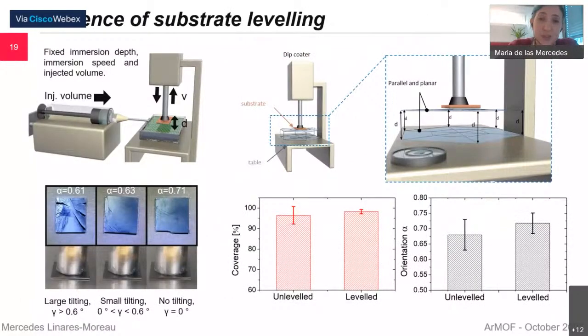The first parameter that we identified as very relevant was the leveling of the substrate. It's not that we tilted the substrate on purpose, but we found that typical dip coater devices do not have such a good precision in leveling the sample. And actually, initially, with a tilting of the sample that was almost imperceptible to us, we found that this was impacting the quality of the samples a lot.